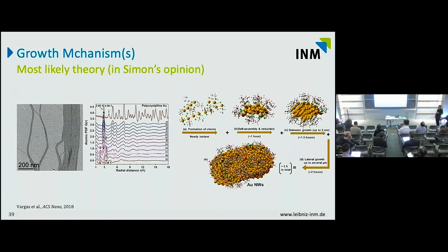I don't think it's really known yet, and different ideas still compete. But there are some structures that are very uniform along the length in thickness, which already excludes many proposals, in my opinion. However, maybe it's like a very long cluster, and the internal gold structure has some kind of magic configuration that geometrically prefers a certain thickness, because it's also not possible to grow them to any thickness you like. You get a certain thickness, it's reliably the same, and you cannot vary it. Thank you.